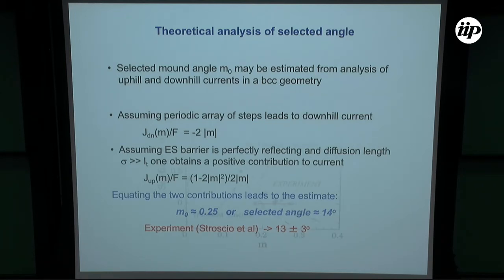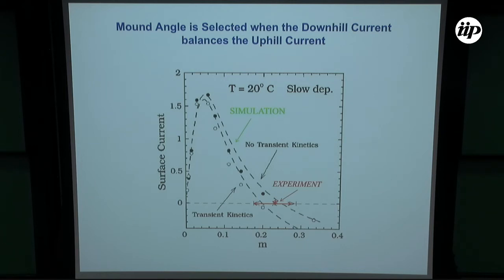So to show you that, here are our final results from the simulations. The symbols in this picture and the dashed curve are the expressions that I showed you for the current. This is the total current on the surface. Initially, when the slope is small, the current increases, and as the slope gets bigger and bigger, the downward current increases, and eventually, if the slope is high enough, you have a negative total current. And where they balance, where the total current is 0, is where the angle is selected.